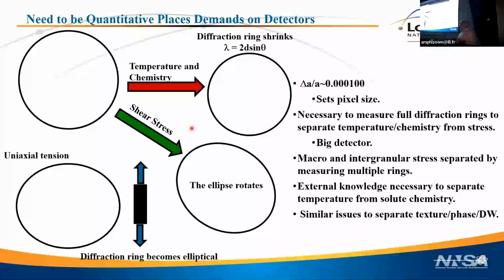You can't get stress without assumptions, without having more measurements. And if you're trying to go very fast, you don't have time to rotate your sample, or if your sample is in an additive manufacturing rig, you might not have time or the ability to rotate your sample, which makes getting stress and texture another step harder because you inherently need a 3-dimensional measurement unless you can make some symmetry arguments, and I will do that as we move on.